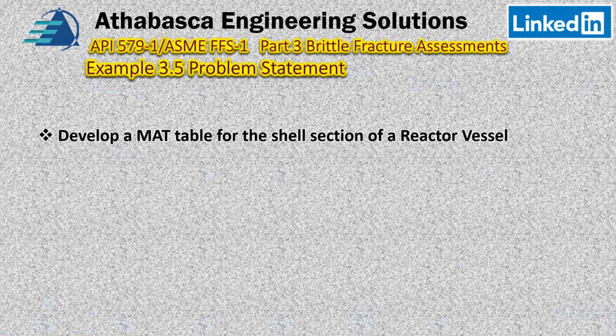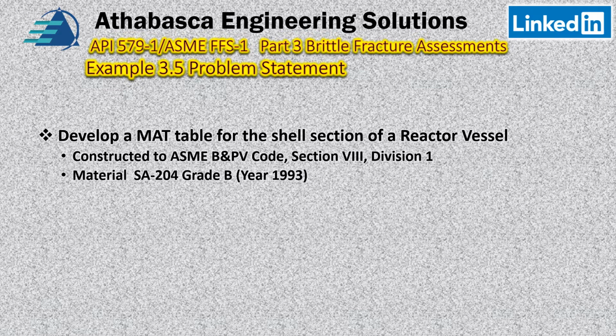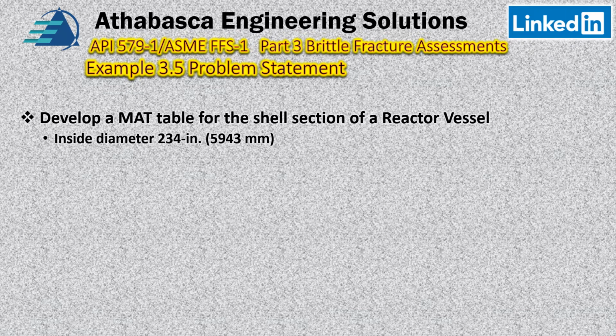The problem is we're going to develop a MAT table, the minimum allowable temperature for materials, for the shell section of a reactor. We're given that the vessel was constructed to the ASME Boiler and Pressure Vessel Code, Section 8, Division 1, and the material was SA-204 Grade B, 1993. The example gives the allowable stress, and we found it to be 17.5 ksi or 120 megapascals. Furthermore, the inside diameter is 234 inches, 5.943 meters, and the thickness is 2.72 inches or 69 millimeters thick.